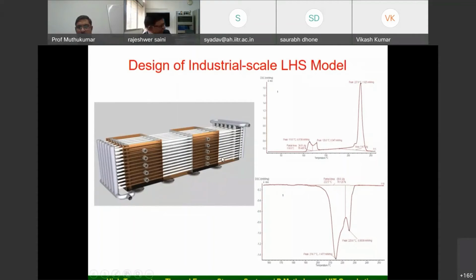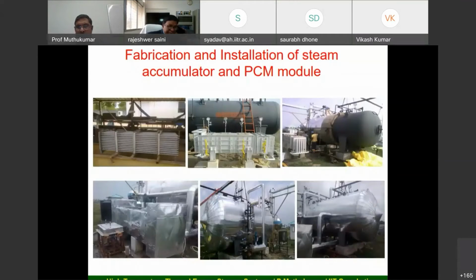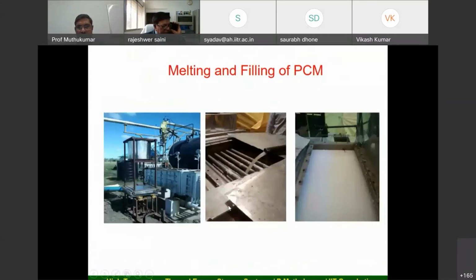Again, it's a cascade system. There are about 144 tubes which are half-inch, and we have done the detailed DSC analysis also, and we found out the melting temperature range and their respective enthalpy, and based on that, you can see here how they were integrated with the steam accumulator. There are several thermocouples for capturing the temperature history during the melting of the PCM, and this is insulated. Because we have to completely make the PCM liquid, then you charge them carefully.